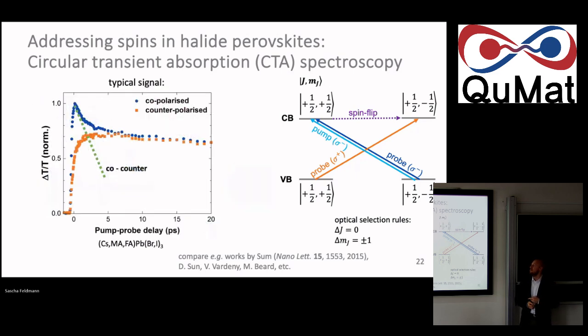And if you do that, you really see what I predicted would happen just now. That is to say, a co-polarized measurement here in blue would give you this prompt rise and then decays with the excited state. And the counter-polarized one really takes some time for a spin flip to occur to build up, and therefore has this delayed rise time here. And if you just subtracted co minus counter, you would be left with this sharp drop, which looks like mono-exponential. And that would be really on the order of 2 or 3 picoseconds max for all of these materials. So this has been shown, and it is quite beautiful that you can just this simply optically read out a spin lifetime of, say, 3 picoseconds in this material.